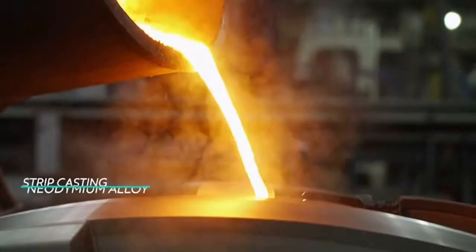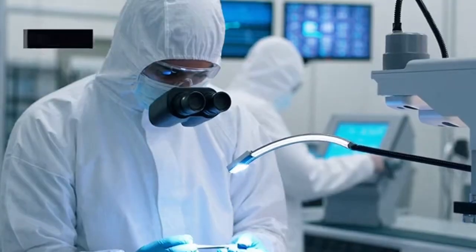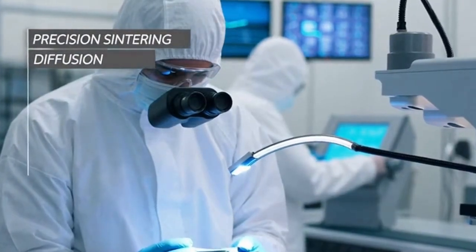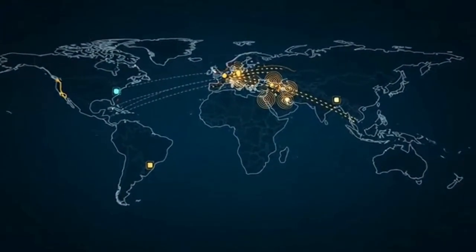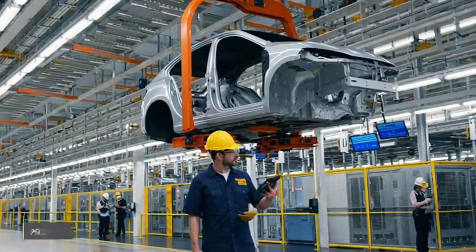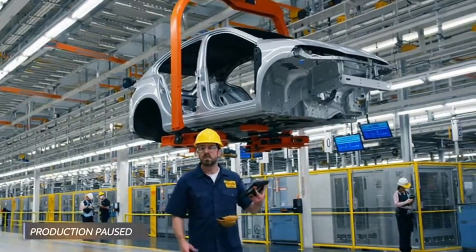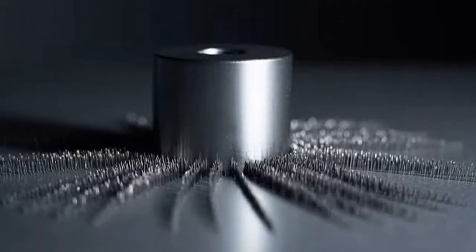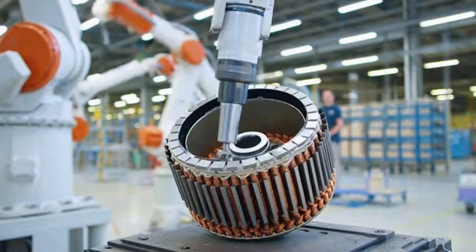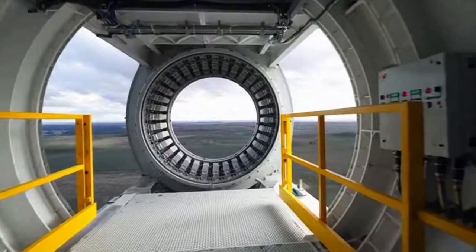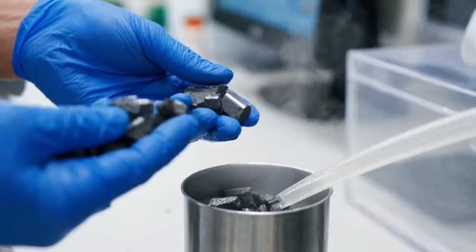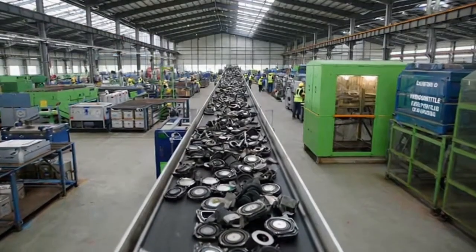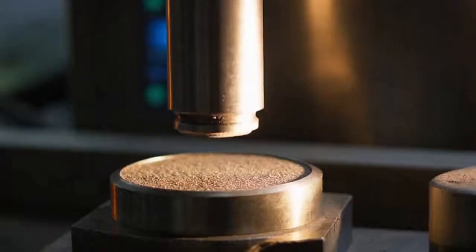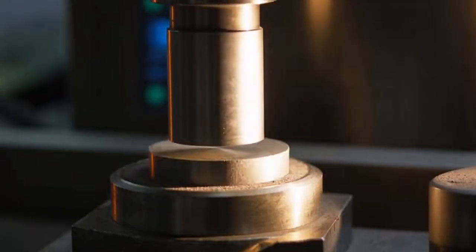expertise and consistency. Then there's metal making, turning those oxides into metal of the purity and consistency that downstream alloy casting expects every time. Then the alloy and magnet fabrication: strip casting that must freeze the alloy into a narrow grain size distribution, hydrogen decrepitation that should crack the material at the right places, pressing and sintering steps that must lock in the easy magnetization direction precisely where you want it, grain boundary diffusion that adds dysprosium or terbium exactly where each grain needs a little extra courage.